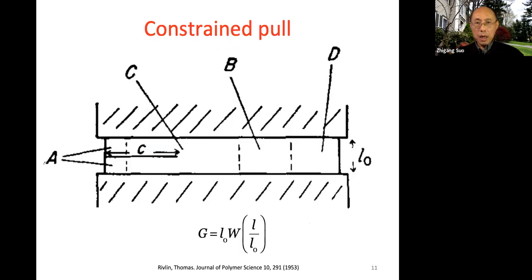Now, here's another way to measure it. I won't go into detail. The only thing I need to tell you is if I have some rubber-like material, all I need to do is grip this material, make an initial cut, and pull it. When I pull, this crack opens up and blunts, and at some critical amount of pulling, the crack starts to move forward. That's the point where we measure toughness. Much toughness is measured this way.